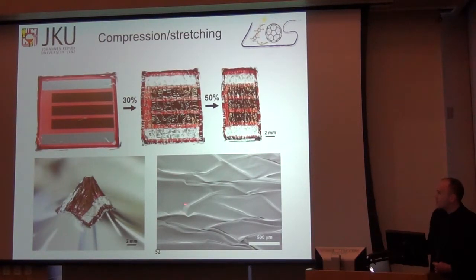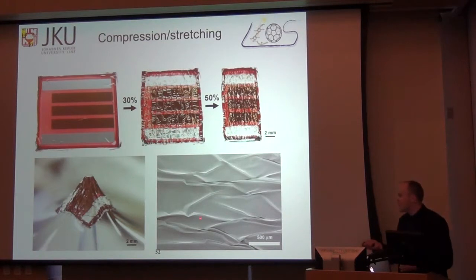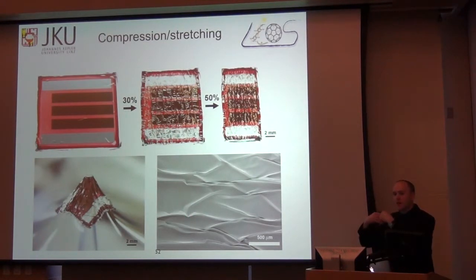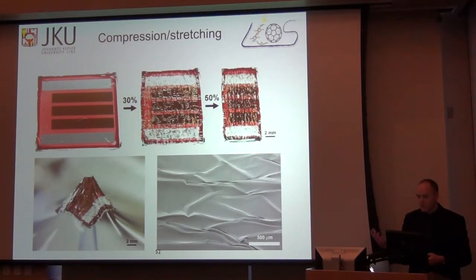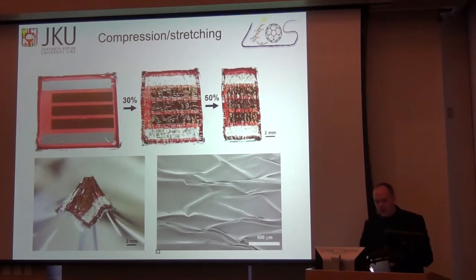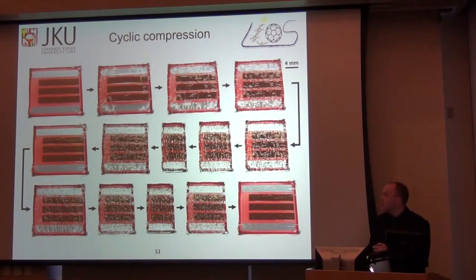You can see that most of the area is flat and safe, but there are some wrinkles that are tightly bent radius, and some points where the wrinkles come to a junction, which are very sharp. And those are likely the formation nuclei for cracks, which cause the ultimate degradation of the solar cells, which I'll get to in a minute.